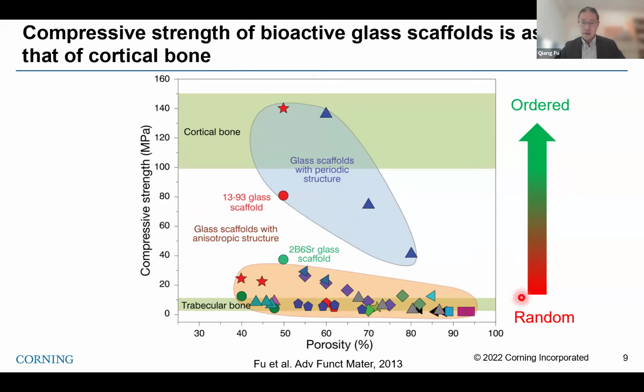This compressive strength versus porosity plot shows the range of strengths we can make out of glass scaffold. As you can see, when the structure changes from random to ordered, the strength increases from those comparable to trabecular bone all the way to those comparable to cortical bone. Again, these high strength glass scaffolds are made using a 3D printing technique. With all this great microstructure and very high strength, we have high hopes for use as implants for load-bearing applications.